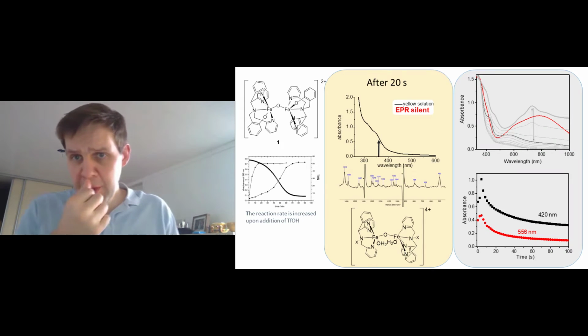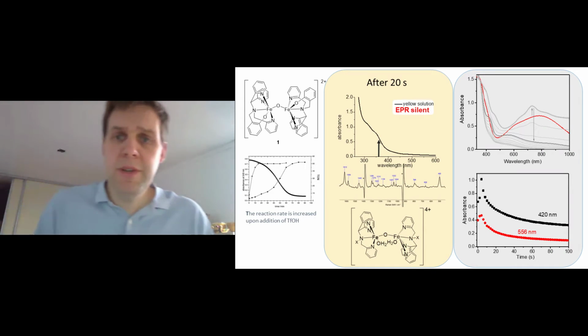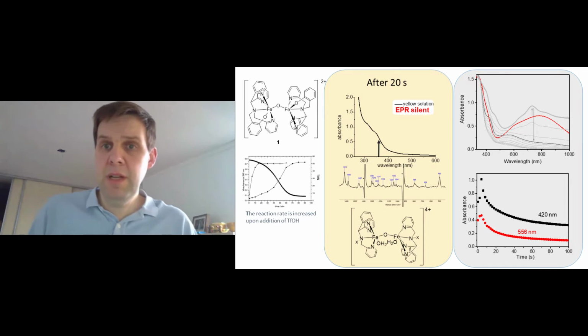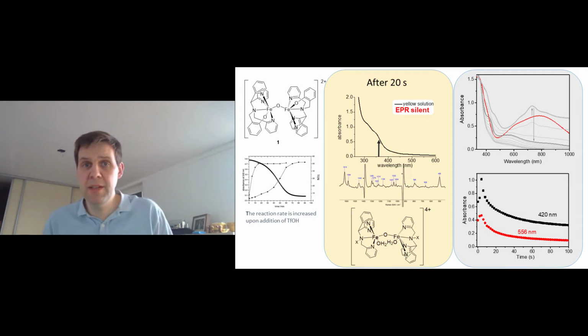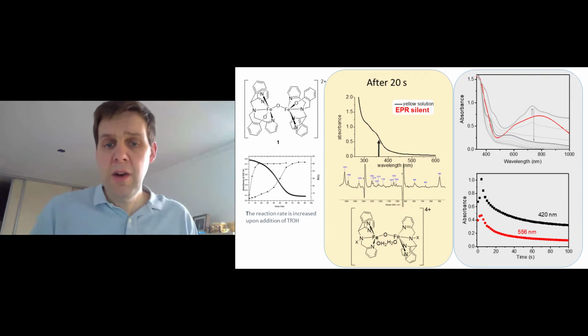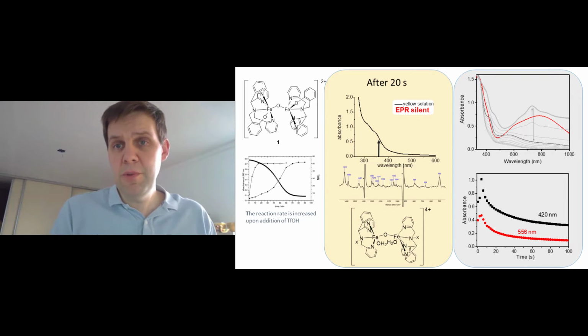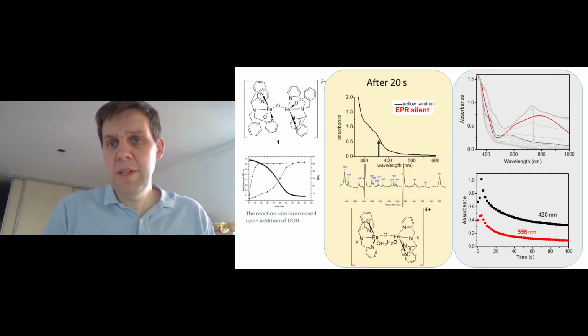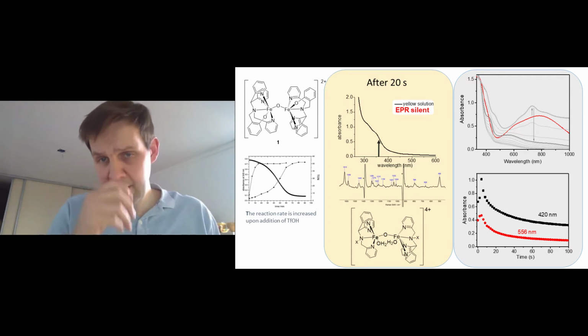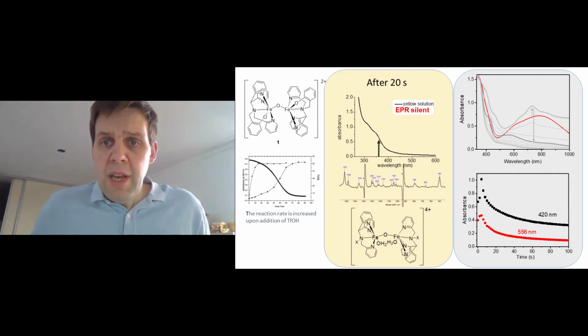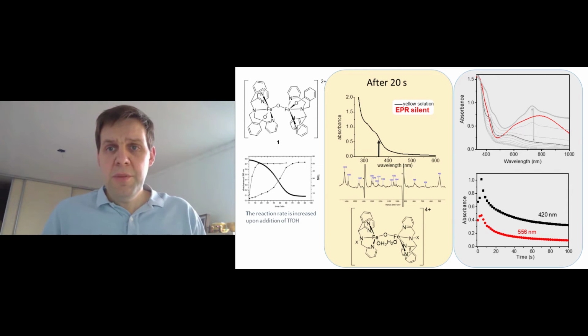Now, we can follow by UV-vis spectroscopy with fairly high time resolution. And well, every 0.1 of a second or every half second gives us enough time resolution to see that our initial absorption, as soon as we add the hydrogen peroxide, we see a very broad increase in absorbance over the entire spectrum. And within a few seconds, we see a decrease. And then there's appearance of a band around 600 nanometers, which then decreases itself to give us this final spectrum over 20 seconds. So we have very little time to catch whatever species are present there.